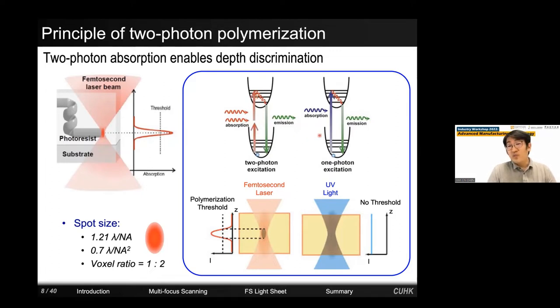In comparison with a conventional stereolithography process, the two-photon process has depth discrimination. In other words, it only polymerizes material within the focal point that's much smaller than a size of 1 cubic micron. And it is also very sensitive to a polymerization threshold. So in other words, if you finely control the laser power, you can write structures much smaller than the diffraction limit. And that's why much smaller features than the wavelength of light can be created.